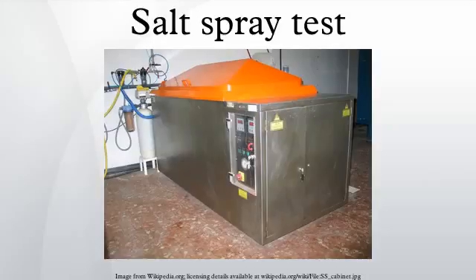Requirements shall be agreed between customer and manufacturer. In the automotive industry, requirements are specified under material specifications. Different coatings have different behavior in salt spray test, and consequently, test duration will differ from one type of coating to another. For example, a typical electroplated zinc and yellow passivated steel part lasts 96 hours in salt spray test without white rust. Electroplated zinc-nickel steel parts can last more than 720 hours in NSS test without red rust. Requirements are established in test duration, and coatings shall comply with minimum testing periods.